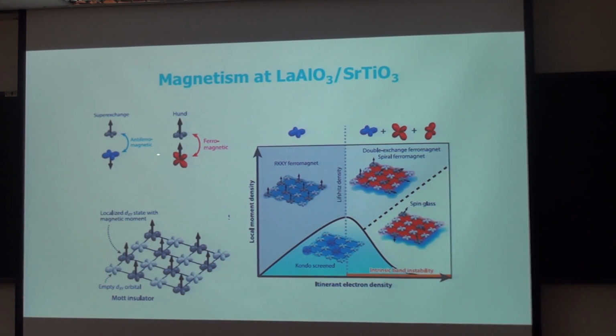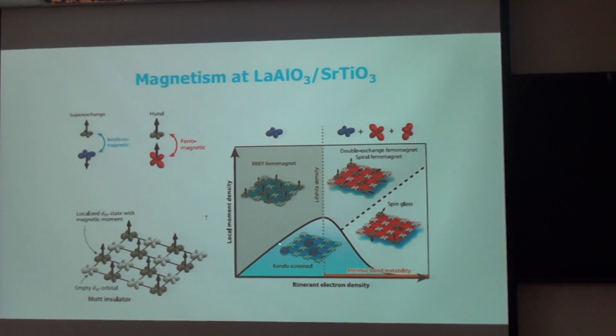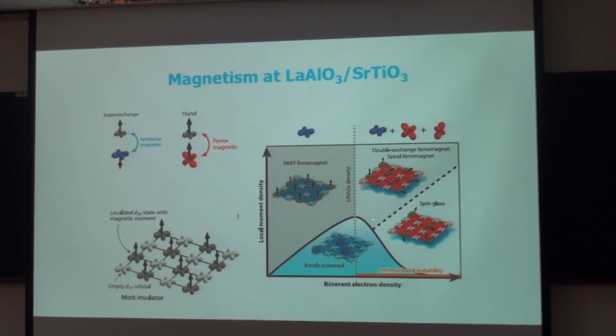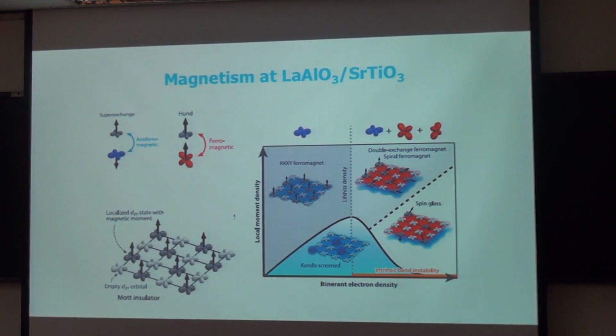Theoretically, depending on the orbital occupation, we can distinguish two types of exchange interaction. Between the same orbital, we can find the magnetic exchange interaction is antiferromagnetic. Between different types of orbitals, the magnetic exchange interaction is ferromagnetic. So depending on the density of the heterointerface electron density, as well as the localized orbital magnetic moment, we can tune the magnetic ordering of this system from a Kondo screened system to the double exchange ferromagnetic system.